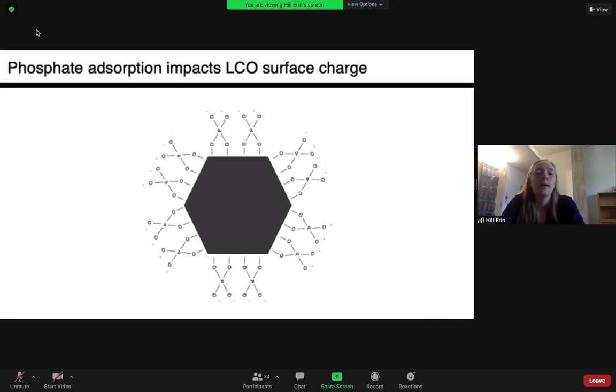The change in surface charge may allow for electrostatic stabilization of the nanoparticles, and so to investigate this, we measured zeta potential through laser Doppler microelectrophoresis. This measures the movement of charged particles in an electric field. The movement is a function of particle charge, the electric field, and the solvent it's in.